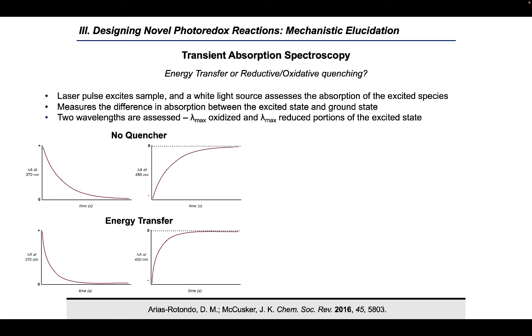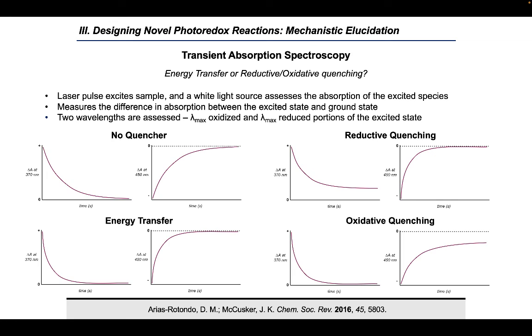An energy transfer mechanism is indicated by full relaxation back to the ground state at both of the assessed wavelengths at the same rate, since in an energy transfer mechanism, both the oxidized metal and the reduced ligand species are lost simultaneously upon quenching. Whereas with reductive or oxidative quenching, depending on which it is, you will not observe full relaxation back to the ground state in either the lambda max of the oxidized metal or the lambda max of the reduced ligand. Next, we will address some common troubleshooting in developing your own photoredox reaction,